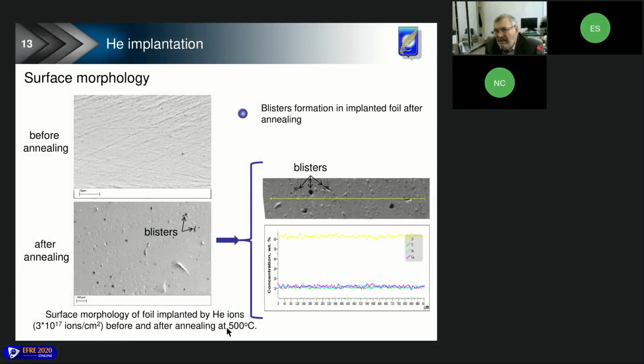So, on this slide, one can see the surface morphology of the implanted foil before and after annealing. Annealing at a temperature of 500 degrees led to surface blister formation. This one, covered blisters and uncovered blisters. Here they are at high magnification.